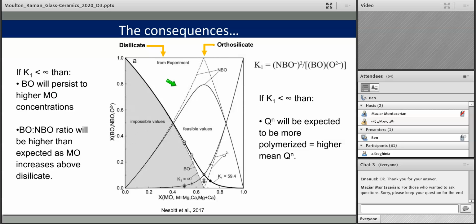So let's consider a couple of consequences of equilibria less than infinity, and in this example, we'll choose a K1 value of 60. First, bridging oxygen, remember it's at 100% here, will persist to higher compositions than expected, and even, in very small amounts, up until you have 100% metal oxide. Conversely, if there's more bridging oxygen, there is less non-bridging oxygen, and so the non-bridging to bridging oxygen ratio will change, and you'll have some situation here. As a third and final consequence, if there is some bridging oxygen, we know that there must also be some small amount of free oxygen.